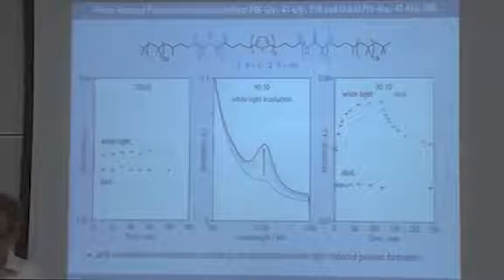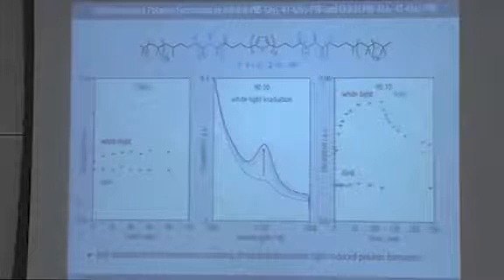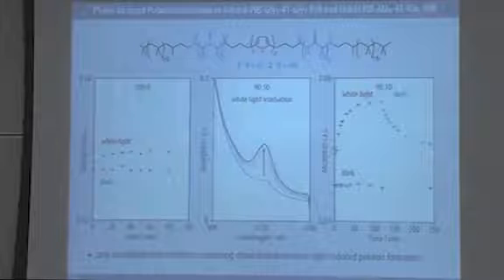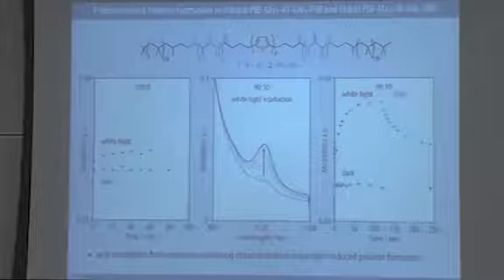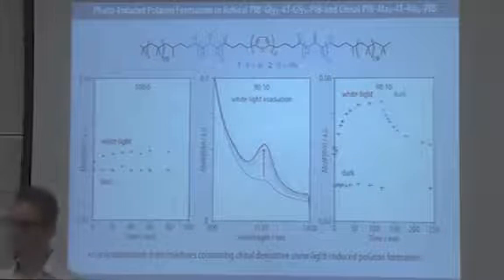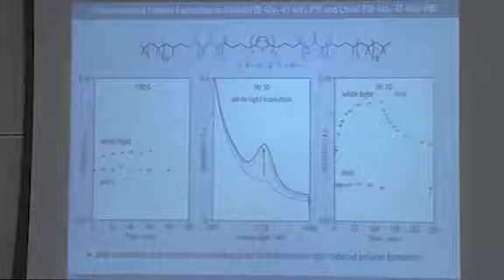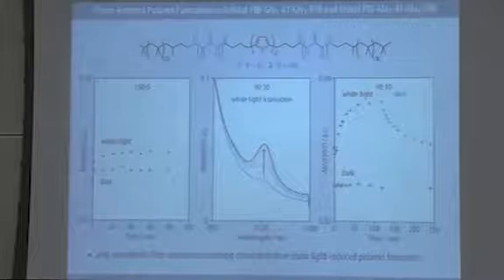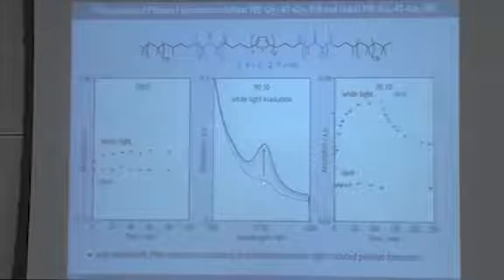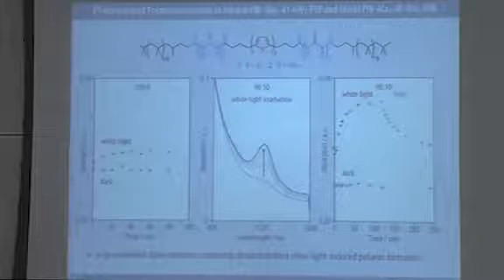It's not only important that the pi conjugated segments inside the nanofibrils are closely packed, which I hope I've been able to convince you that they are. It's also important that they're helically packed and that somehow this core of the nanofibrils is surrounded by something else. Yeah, it seems to me that it is like this. If we add 10% of the chiral molecule, then we're back to a situation where we can form the radical cations by exposure to white light, and the intensity of that peak actually scales with the amount of chiral additive we add.